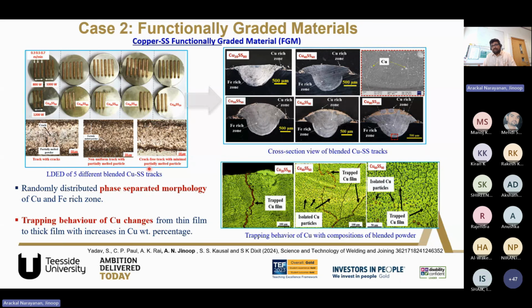We could see a lot of cracking, and the cracking tendency reduced when we increased the copper composition, and the cracking behavior also changed with respect to the composition of the material. It was tearing at some part, and it was also porosity induced cracking at some point. But as the copper composition increases, more liquid film is available to fill the cracks, and we could reduce the cracking to some extent.